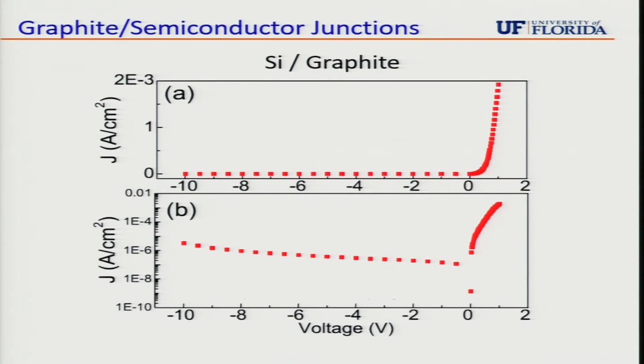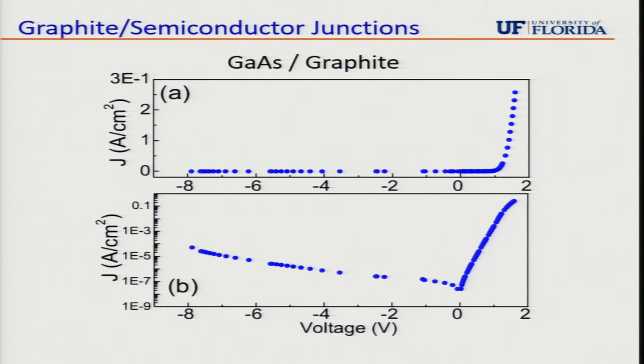Here's a typical junction. We make these plots on a semi-log scale, and you can see this is a semi-log scale, and this is a linear scale, so you see a very strong forward bias and a very low current in reverse bias, here and here. That's a log scale. That's a linear scale. That's silicon on graphite. Notice that it works for gallium arsenide very well. And important, on Schottky barriers, if you have a linear region here on a log scale, that enables you to use the thermionic emission equation and get the parameters of the barrier very easily. And I'll show you how you do that.